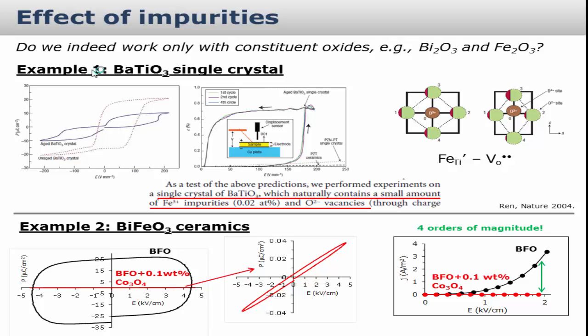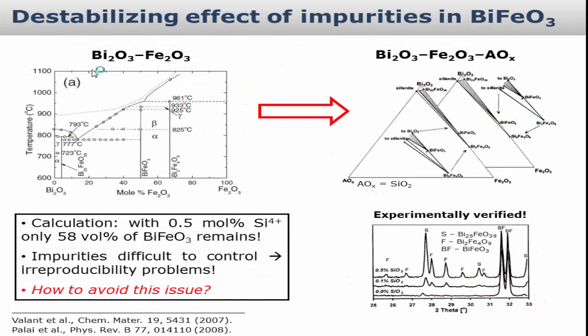If you measure current, for example, we were able to see, at a certain field, four orders of magnitude difference in the current response between the BiFeO3 samples when you just added a bit of impurity. So this is a problem. Impurities in a relatively low amount can strongly determine your processes and properties. In all these cases, we usually assume that the impurity goes into the perovskite, somehow incorporates, and makes an oxygen vacancy or whatever. But in the case of BiFeO3, especially when you're processing it, one should think about incorporation of these impurities in a different way, because the same impurities can go not only into the perovskite but also into the secondary phases. And this is where you get to this phase diagram here.